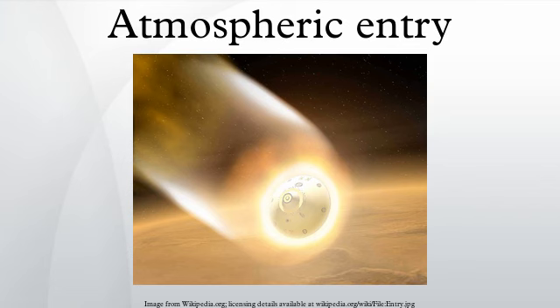The MSL aeroshell TPS is currently designed to withstand a peak heat flux of 234 W/cm². The peak heat flux experienced by the Viking 1 aeroshell which landed on Mars was 21 W/cm². For Viking 1, the TPS acted as a charred thermal insulator and never experienced significant ablation. Viking 1 was the first Mars lander and based upon a very conservative design. The Viking 1 aeroshell had a base diameter of 3.54 meters. SLA-561V is applied by packing the ablative material into a honeycomb core that is pre-bonded to the outer shell structure, thus enabling construction of a large heat shield.